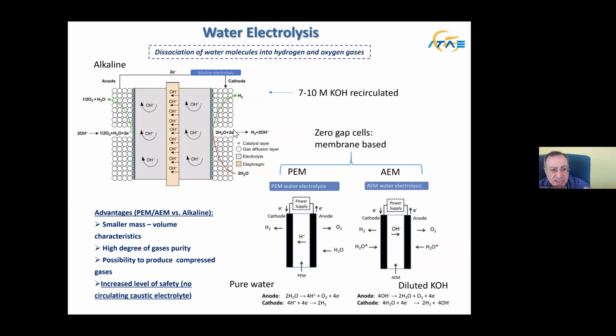The difference is that in the alkaline electrolysis, we use just a porous separator. I'm showing here this porous separator, and we have some recirculation of concentrated KOH, of caustic solution. So this is the approach used in the alkaline electrolysis. And we have at the cathode hydrogen evolution and migration of hydroxide ions to the anode, where we have oxygen evolution.